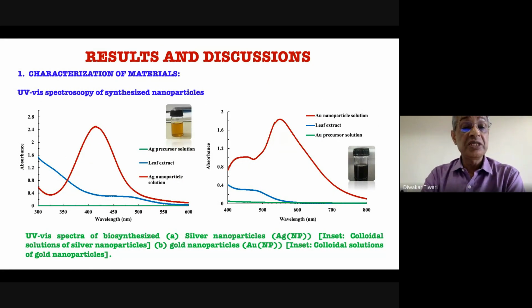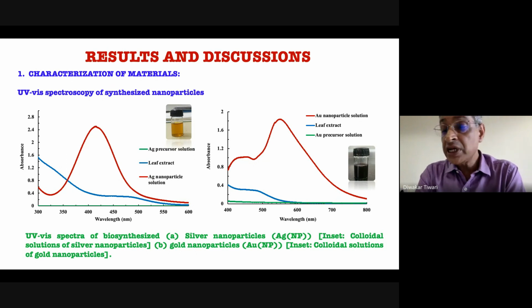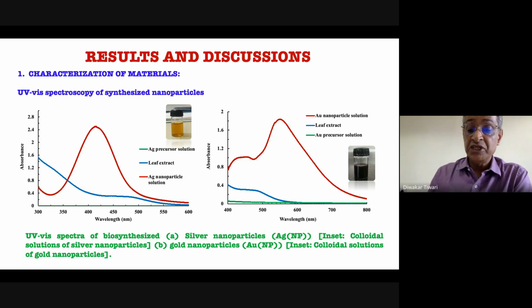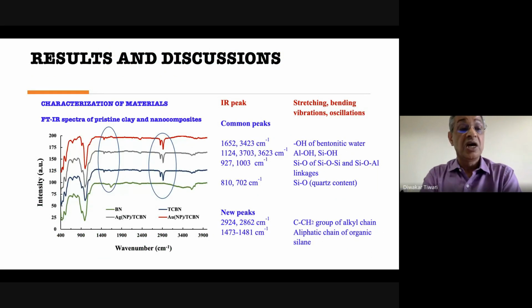Very quickly, I will go through the silver and gold characteristic peaks from the UV-visible spectra that we could get. In the inset, we have shown the yellow color of the silver colloidal particles, and on the right-hand side, the gold nanoparticles in liquid form. We have taken the UV-visible, and these are the characteristic spectra. Then we obtained the FTIR spectra for these materials, through which we can confirm that the organic silane has been introduced, as marked here.